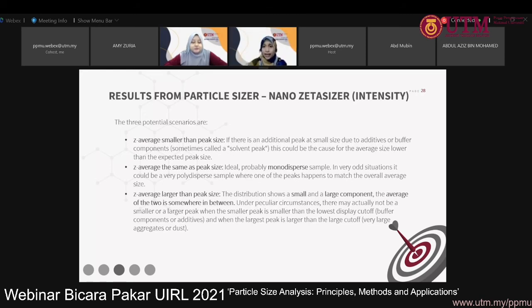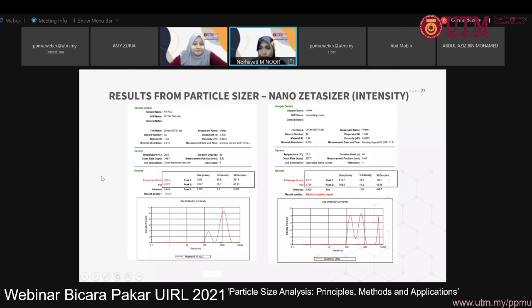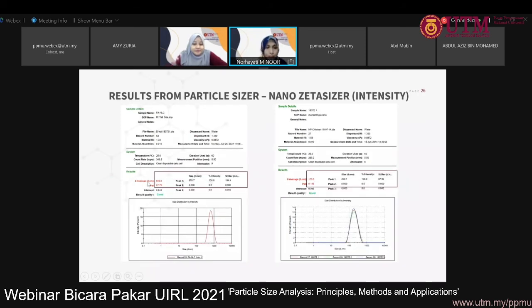When I say the Z average and the peak size, you can see from here. So this is the Z average for this first result, and the PDI is very small, 0.175, but the peak is 670. Why do I have intensity of 100%, and the size is 670, but I still have a small PDI and the Z average is 500? It could be due to the small population here, which they still take into this result to get the mean of the particles. So that's why my Z average is smaller than the peak size.